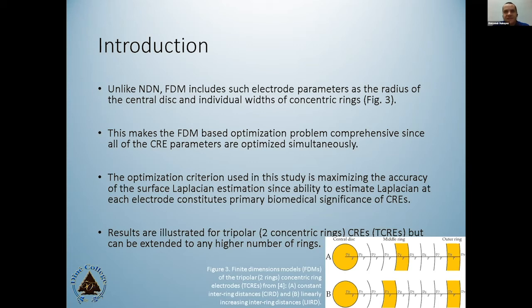We decide on the number of rings, on the size, on inter-ring distances, the width of individual concentric rings, the radius of the central disk, which finally made this optimization problem somewhat comprehensive, or actually comprehensive. So the idea was the following. We have one criterion in this optimization problem, which is maximizing the accuracy of the surface Laplacian estimation. The higher the accuracy of the Laplacian estimation, the better the diagnostic yield of the resulting signal. We illustrate the solutions that we obtained for the case of tripolar concentric ring electrode, which means a central disk and two concentric rings. But as you will see, they can be extended for any higher number of rings. The principles that we were able to formulate based on the optimization result allow us to extend them to any number of rings beyond 2.